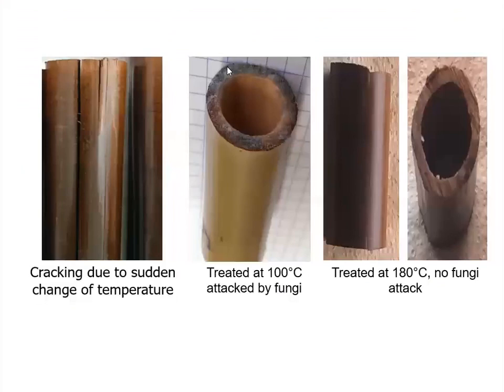But when it is treated at a high temperature, around 180 to 200 degrees centigrade, no fungus is found to have attacked the bamboo. These are the different uses of thermally modified bamboo. More stable and durable, thermally modified bamboo products can be used like hardwoods. Good quality hardwoods can partly be replaced by thermally modified bamboo. These are the different applications where we can use it: flooring, furniture, handicrafts, panel products.